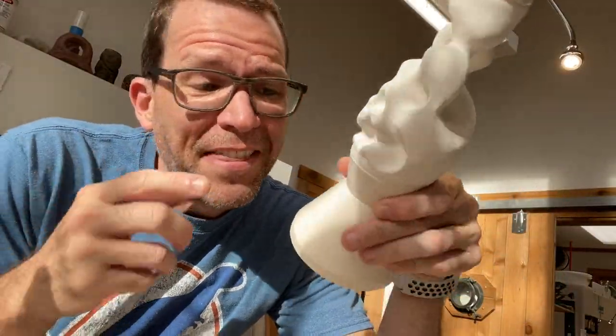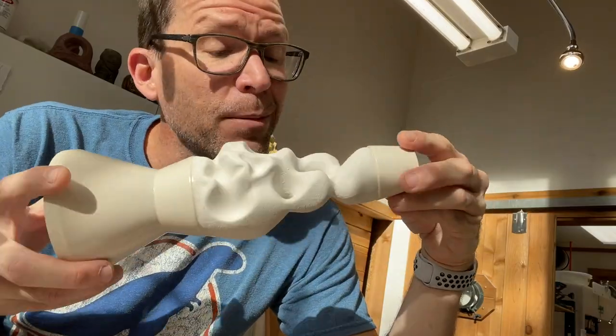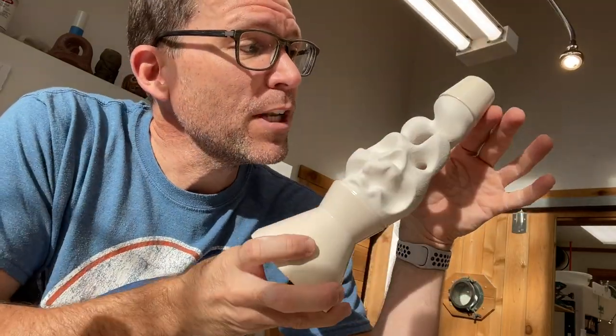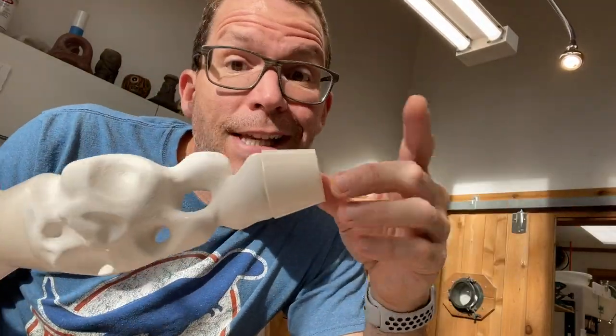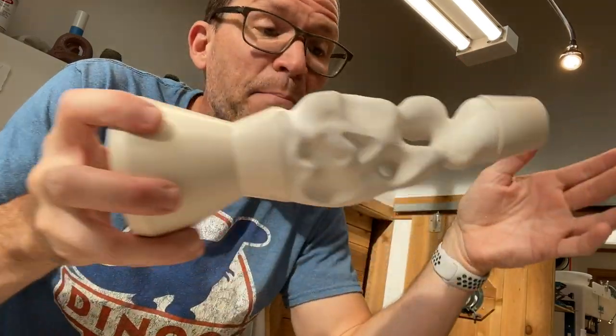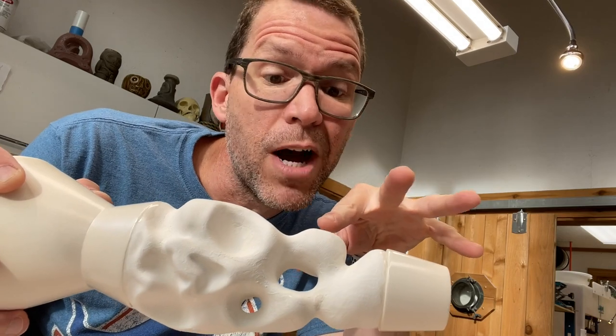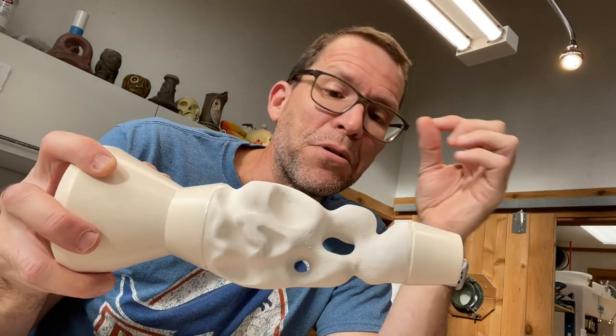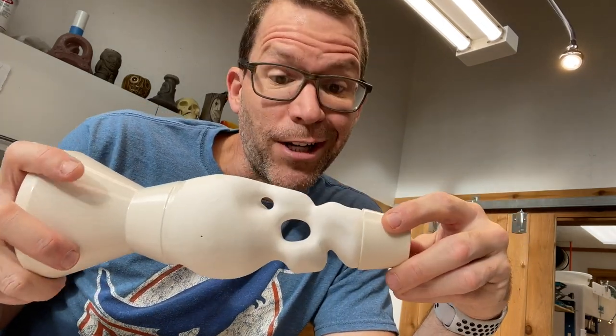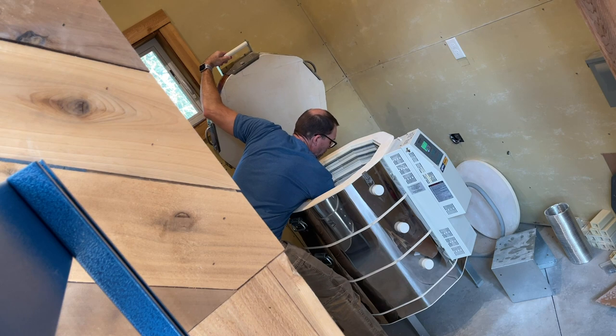I've got two coats on there. I'm going to do a third just in the areas that I knew were really thin, and we're going to put it back in. I don't usually do brush applications of glaze, but this stuff seems to flow pretty well. Why am I not putting it on the tops and the bottoms? I really liked the way they look — it goes to satin and then almost to matte on the top. I'm not going to be putting luster on the top and the bottom, just in this middle section. So I'm putting the glaze on thick in that area. It's time to go back into the kiln for glaze firing number two.